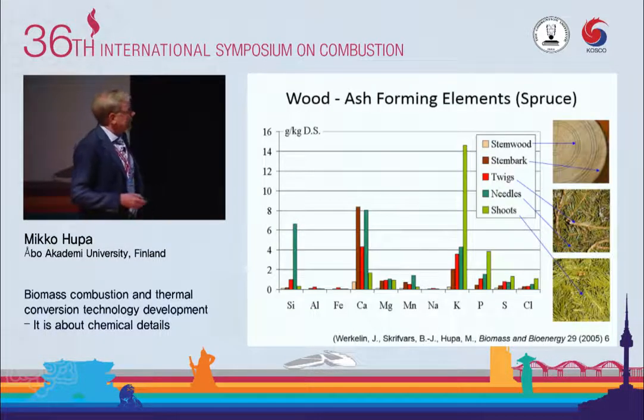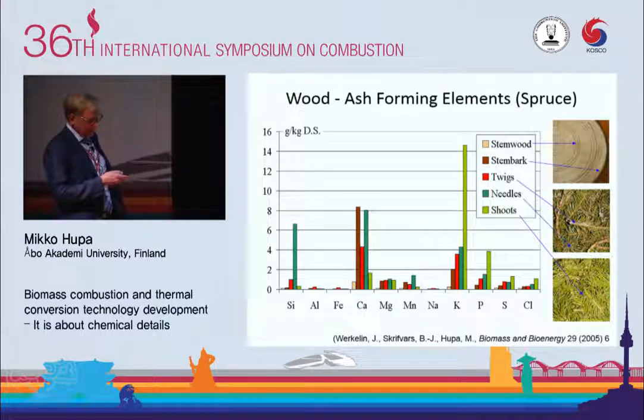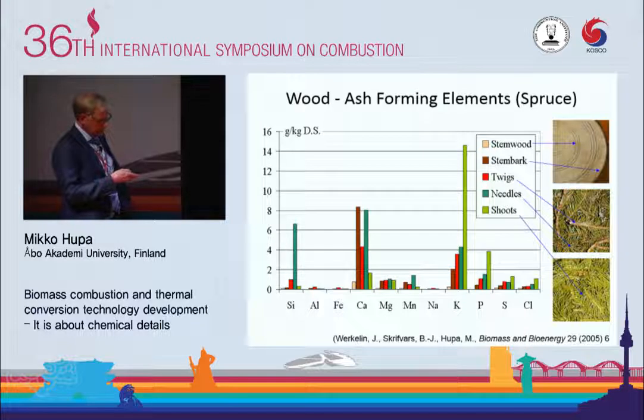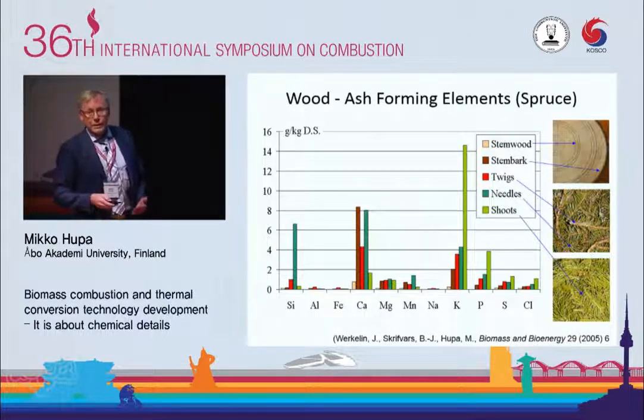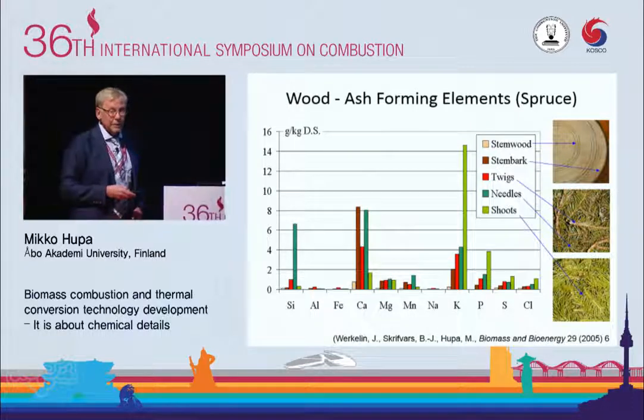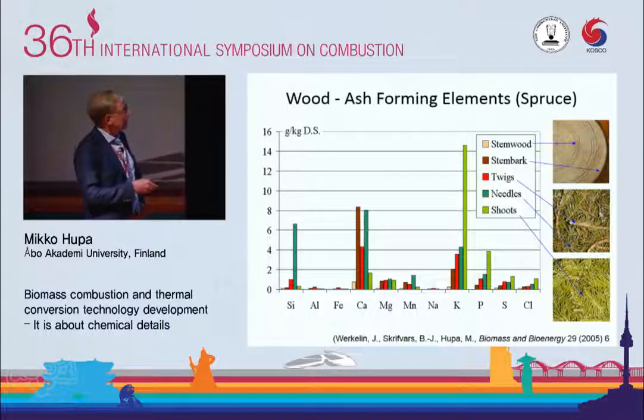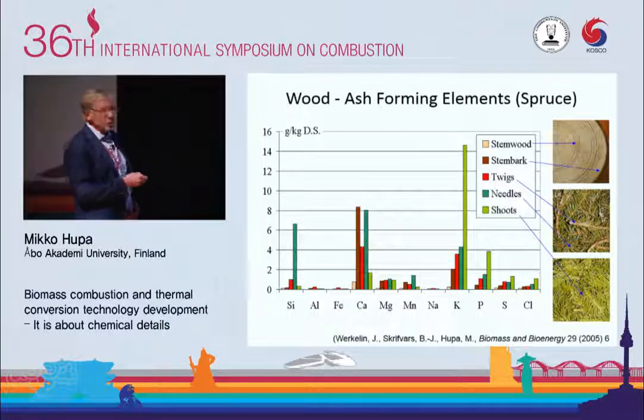However, if we take a look at the composition of wood, you see here immediately that things become more demanding when using green parts of the wood. Look at the potassium content. In wood, it is very, very low. In bark, higher. But when we go to twigs, the small branches, it's even higher. And needles. And if somebody would be interested in just analyzing the annual growth, the potassium content is extremely high. So the more green material is there in the mix, the higher is the amount of ash-forming elements, and it concerns almost all of the elements.